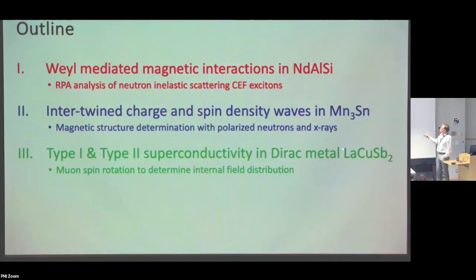And for this material, I'm going to talk about how we use both polarized neutron diffraction and magnetic X-ray scattering to determine the magnetic structure and analyze the very complex magnetism of this system. In this case, if I get time for it, I'll talk about muon spin rotation or muon spin relaxation that we use to determine the internal field distribution in the superconducting state.